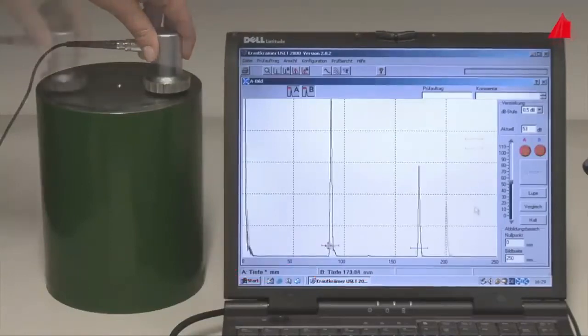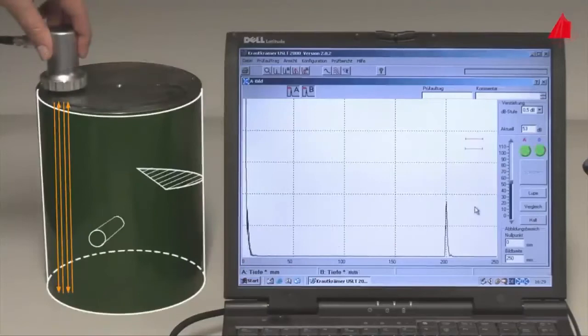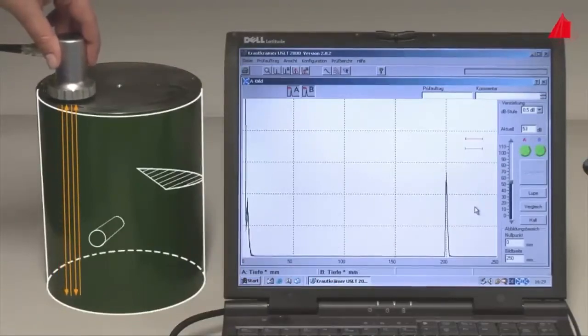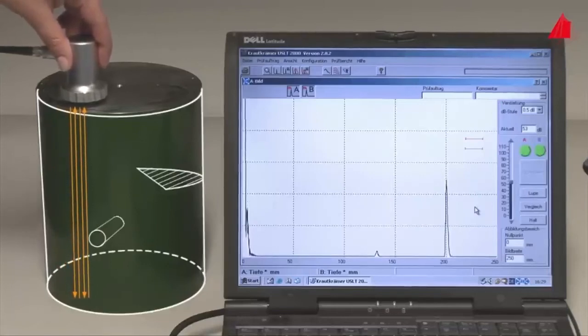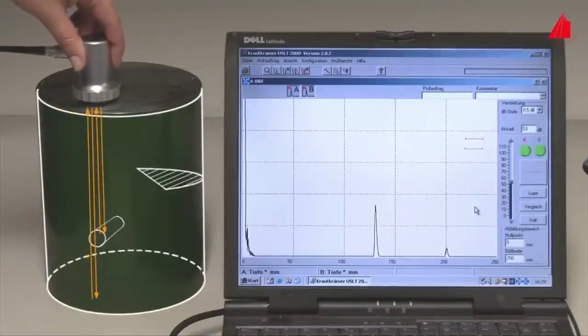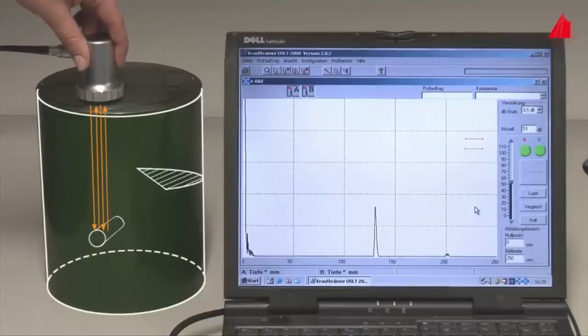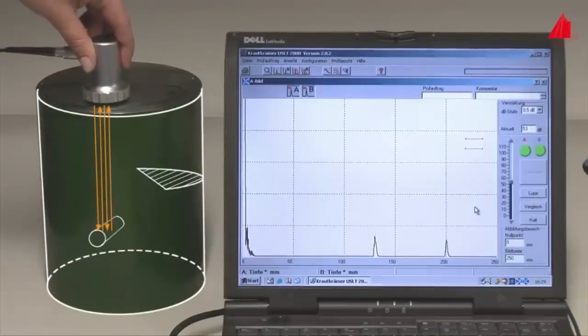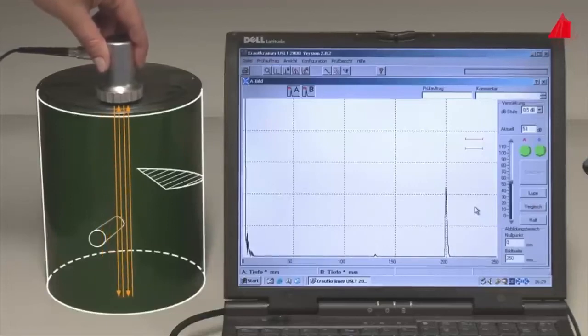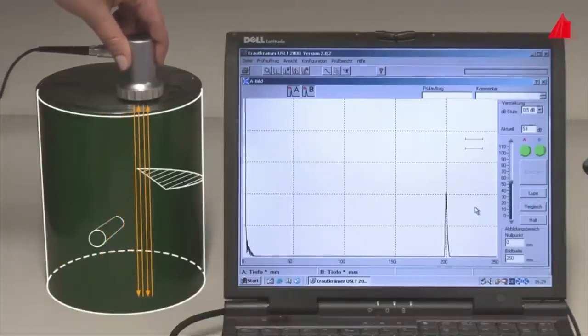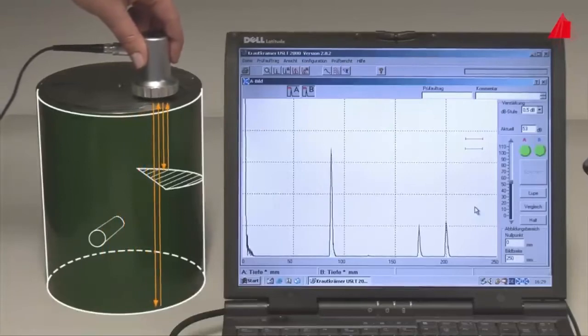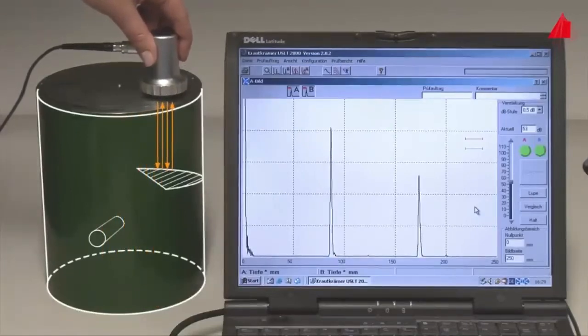And these are the defects. A drill hole and a saw cut. Filled up near the surface and painted, they are not visible from the outside. The drill hole in a depth of 130 mm. The saw cut 87 mm below the surface.